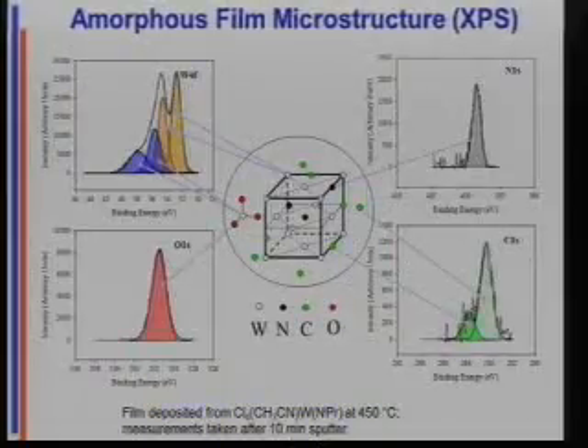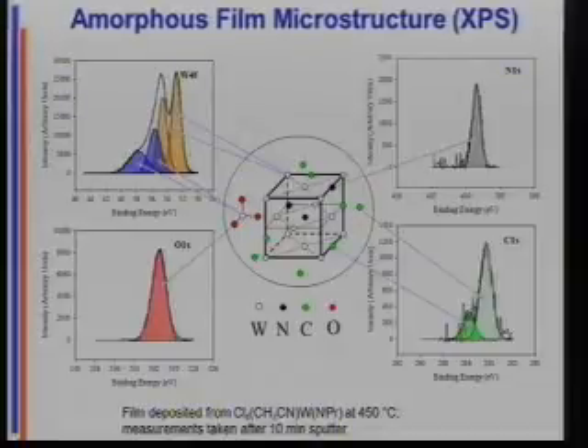That's the crystalline part. For a bulk measurement, you can do XPS and look at this. What we see is that there are two different types of tungsten. One of them corresponds to tungsten oxide. This is from post-growth handling of the samples in the moist Florida air. If you've ever been in Gainesville, Florida in the summer, it's about 95 degrees and 95% humidity. So when you take the samples out, before you can get to the XPS, you have an oxide layer. In fact, you can depth profile from the top of the sample to the bottom, and you watch the oxide content go down as you sputter down.